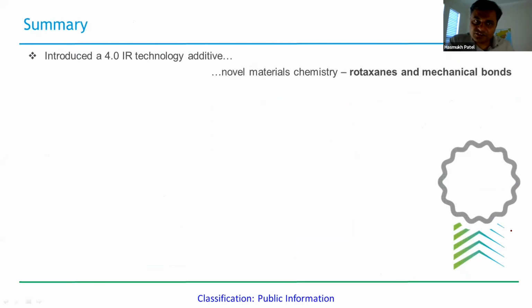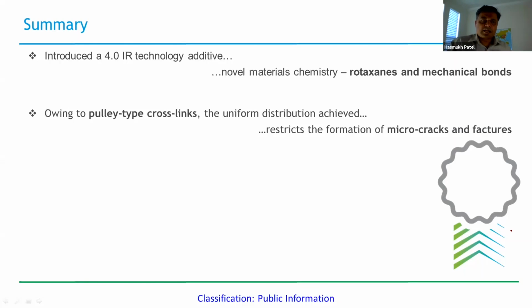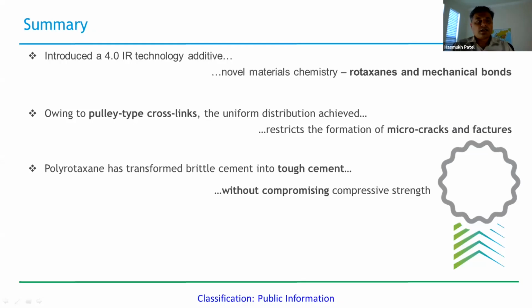So at the end, the take-home message is that we introduced 4.0 IR. In industry, we generally say 4.0 IR, which is the fourth generation industrial revolution technology. We introduced a novel chemistry, which is already established, but we are finding an applied research area for such kinds of materials. We call them rotaxanes and mechanical bonds. Owing to the pulley types of crosslinks, we can effectively redistribute the stresses exerted onto the cement matrix, and it helps in restricting the formation of micro cracks and fractures within the cements, which can help in solving several issues.